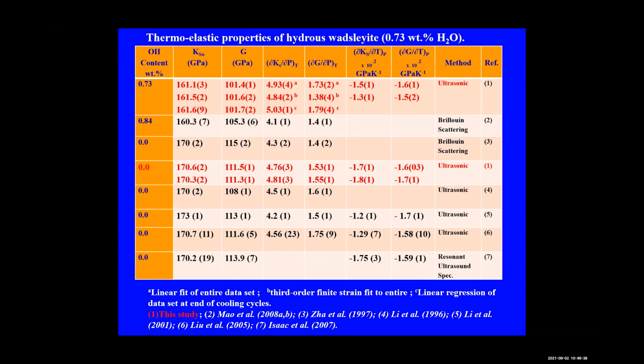Here we summarize the data for the Wadsleyite sample that contains 0.7 weight% water. The first data in red is a comparison of the results that we obtained from linear fit of the entire data set. The second is from finite strain analysis of the entire data set, and the last set of data comes from fitting the linear regression of the data that we obtained at the end of the cooling cycle. As seen in the table, all K and G and their variation with pressure from the 3 analysis methods are in excellent agreement, except of course for the pressure derivative of the shear modulus from the finite strain analysis, which falls out of the mutual uncertainty of the data.